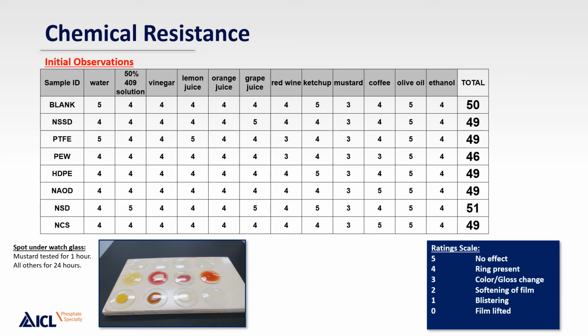I like looking at these results in a cumulative manner, so when you look at the total scores here, you can see overall there is little change to the chemical resistance versus the blank control. The biggest detriment here can be seen with the PEW, and again, I think that lends to the lower gloss that was found with that product, probably making the film more porous. All of the other products are only a point or two away from the control.